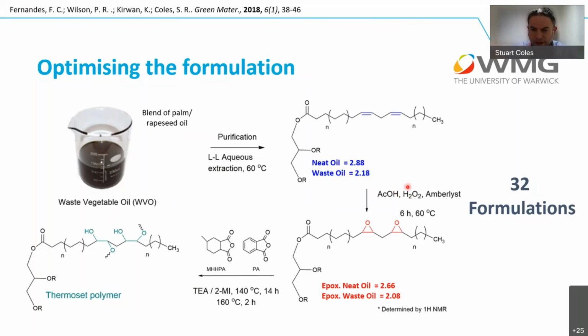We've then got the epoxidation that was controlled. We see a little bit of a drop in the number of epoxy groups because of some of the side reactions going on, but again, it's still relatively in line with the oil, so we're not significantly differentiating between the two at this stage. And then we added the hardener, which effectively ring opens and cross-links and forms that more traditional epoxy resin that we know. With that, we added either the triethylamine or the 2-methylimidazole with one of the phthalic anhydride hardeners, and had a curing regime of 140 degrees for 14 hours and then 160 degrees for 2 hours.